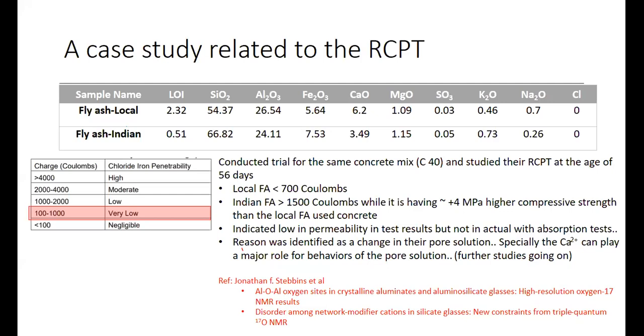Usually in the RCPT test, we take a sample that is 100 millimeter in diameter with 50 millimeter of thickness, like a slice of a small cylinder. Then we apply 60 volts for a 6 hour period, with one edge in sodium chloride and the other edge in sodium hydroxide. We keep it for 6 hours to identify the total charge passed through the particular concrete sample.